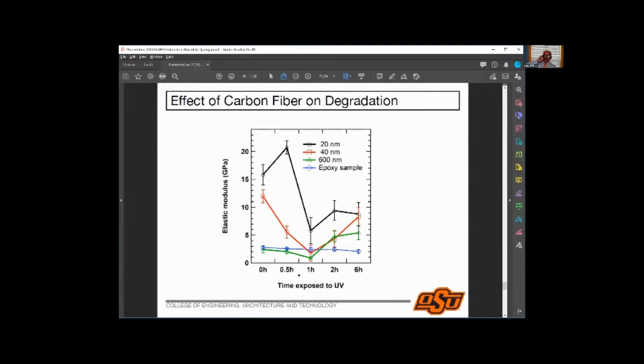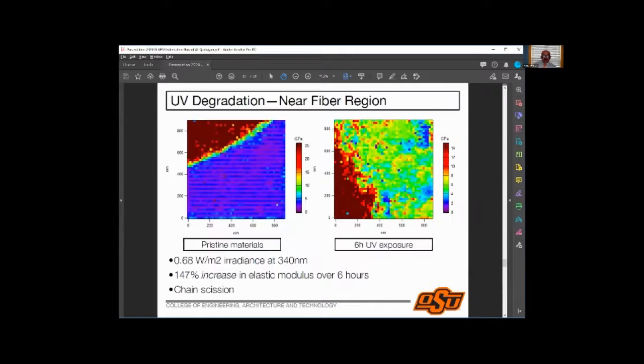So you're starting to see changes in properties. But the fiber matrix interface is still intact. There is no physical damage to the fiber matrix interface. I mean, the fiber matrix interface still exists. If we look at, for example, AFM images of something that has not been exposed to anything and something that has been exposed to 6 hours of UV, we still see that the fiber matrix interface exists. But we start seeing maybe some oxidation of the carbon fiber, maybe some changes in the polymer matrix, but physically there is no damage occurring. I mean, we are very far from any physical damage occurring.